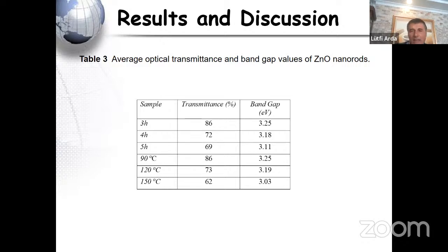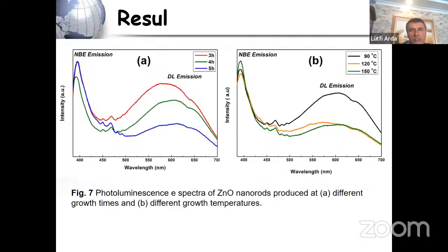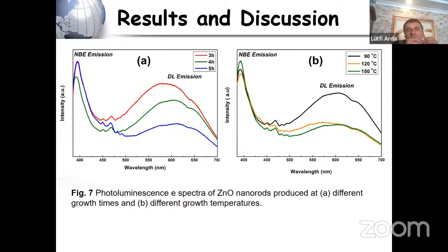Okay, after optical properties, it's the photoluminescence properties. We measured my samples' photoluminescence properties. Why do we use photoluminescence? To study the crystal quality, defect type, and defect density of semiconductor materials, photoluminescence spectra are widely used. Also, electron spin resonance is used for defects. In this work we use only photoluminescence spectra, but we have also some study about electron spin resonance.